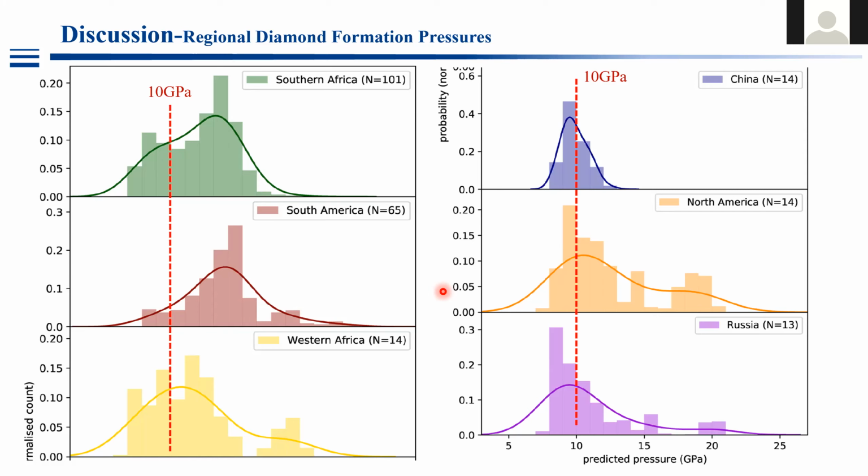I think it's because of the error of the machine learning models, and the authors also analyzed that some natural garnets, with some garnets within the meteorite, have some CPX exsolution, and these models didn't consider the CPX exsolution.